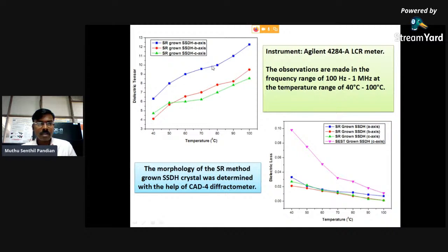This is blue color for A direction, 100, red color for B direction, 010, and green color for C direction, 001. Anisotropy in the dielectric behavior was observed in the case of SR method grown SSDH single crystal. And this is the dielectric loss value of all three directions of the dielectric tensor. These three directions are for the SR method grown crystal, and this is for the conventional method grown crystal.